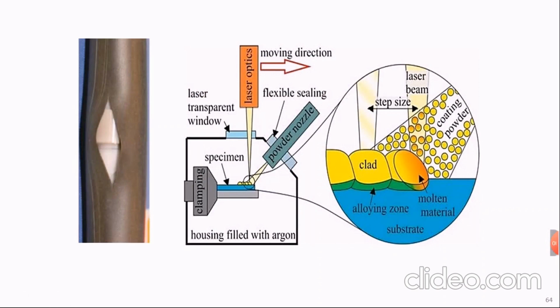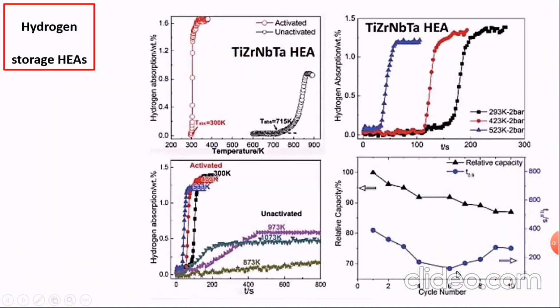In nuclear applications, sometimes a burst occurs in the pipes, and to repair this burst, they apply high entropy alloys by cladding technique. So high entropy alloys prove their efficiency in repairing the nuclear pipes. Also, high entropy alloys are used as fusion plasma facing materials. They have thermal shock resistance. Some other high entropy alloys were designed for irradiation resistance and proved good creep resistance. In aerospace applications, as we said, sometimes it's used for its oxidation resistance characteristics. High entropy alloys also proved success